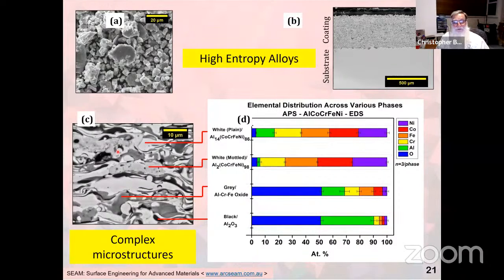Very complex. So a PhD student or two, Amy and Ashok, start getting behind the microscope and they identify all of these phases, with colleagues in Madras, in Chennai. The black phase is alumina, which is good if you want a TGO, thermally grown oxide. We've got a grey phase, a white phase, and another white phase. So now, by carrying out the hardcore science, we're able to identify how this architecture can be described. We are actually putting numbers behind the percentages of these phases and where they're located within the 3 dimensions.